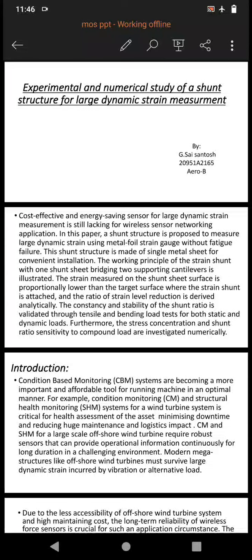In this paper, a shunt structure is proposed to measure large dynamic strain using metal foil strain gauge without failure. This shunt structure is made of single metal sheet for convenient installation. The working principle of the strain shunt with one shunt sheet bridging two supporting cantilevers is illustrated.